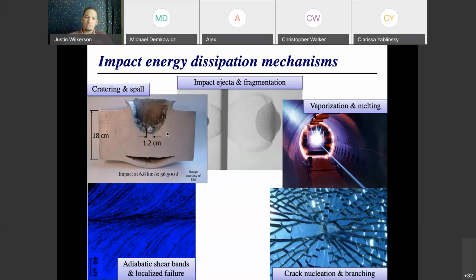But what it cannot do is stop the shock waves that are generated by the projectile impacting the surface of the target material. So when that projectile hits the surface, it sends out shock waves, and those shock waves propagate through the target material. They bounce off the free surface as release waves, similar to that video that we just saw on the previous slide. And when those release waves come back, they can interact with one another and cause a zone of tension in the material. And that zone of tension is where we have all of our dynamic failure, dynamic fracture occurring.